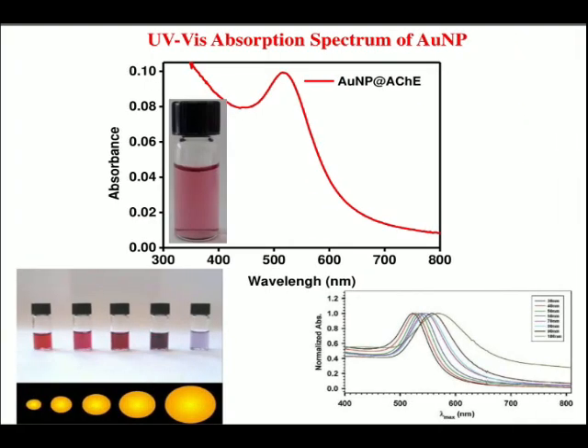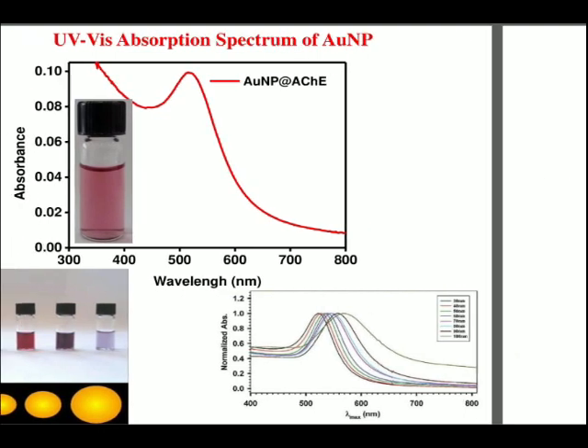And coming to the UV-visible absorption spectrum of gold nanoparticle, here we can see the absorption maximum at 520 nanometer, and the nanoparticle has a reddish color with a size in the range of 5 to 10 nanometer. When the size of the nanoparticle increases, the surface plasmon resonance peak will shift to a higher wavelength region. A red shift is observed and the color of the solution also changes from red to purple with increase in the size of the nanoparticle.